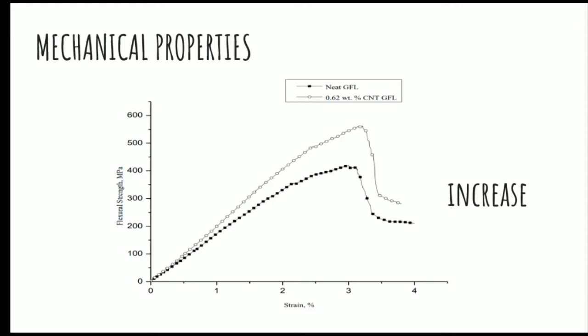Also, the failure strain increased, which indicates an overall improvement in ductility and failure strength. Therefore, the results suggest that controlled growth of carbon nanotubes reduces the failure of glass fiber reinforced polymer composite.